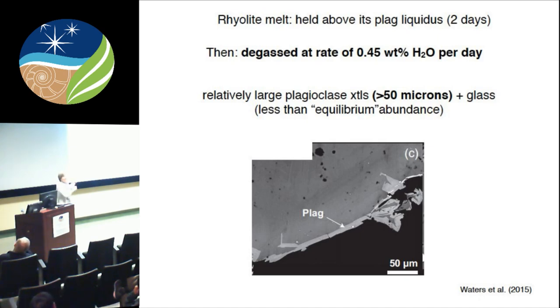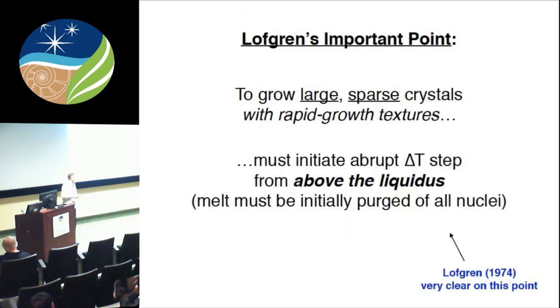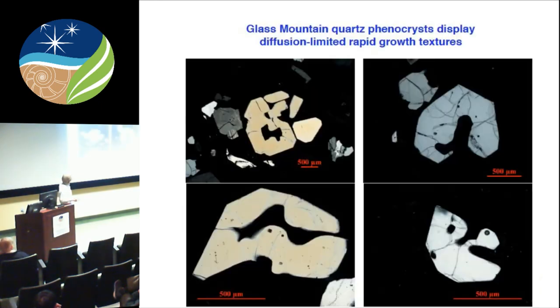And so this reminds us of Lofgren's really important point, which was, if you want to grow large, sparse crystals, and most of us experimental petrologists know this, if we're trying to do some element partitioning studies and we know we need a big crystal, we know to start above the liquidus and do this game. The problem is, back in Lofgren's day, people didn't appreciate how much water was in arc magma. So he couldn't figure out, no one could, how you would get such a big undercooling, like in a magma chamber. It just seemed really difficult to imagine how you could do it. Now we appreciate the concept of degassing-induced crystallization. But you've got to start from above the liquidus. And by the way, these are quartz phenocrysts in the Glass Mountain rhyolites. I would argue that these are rapid growth textures. Sometimes they get interpreted as resorption textures. I think they're rapid growth.